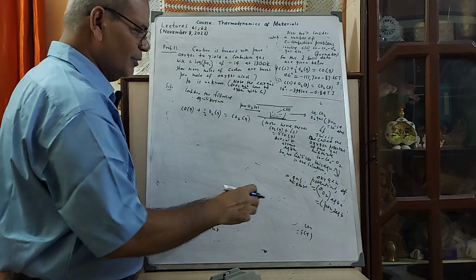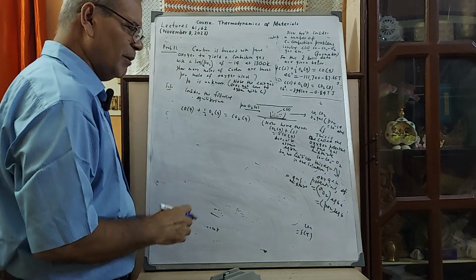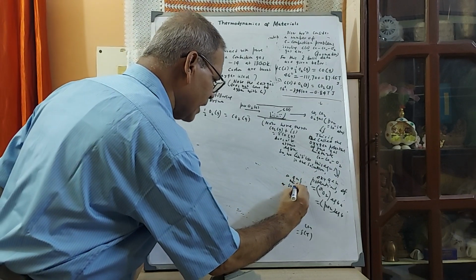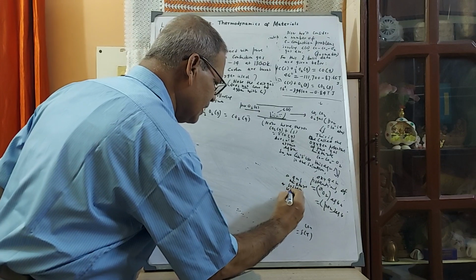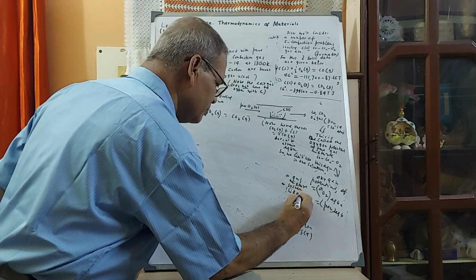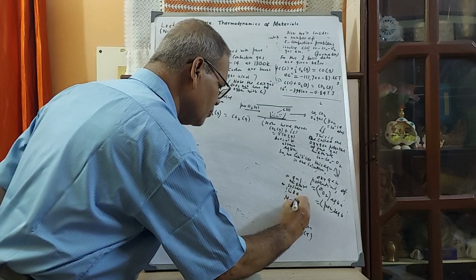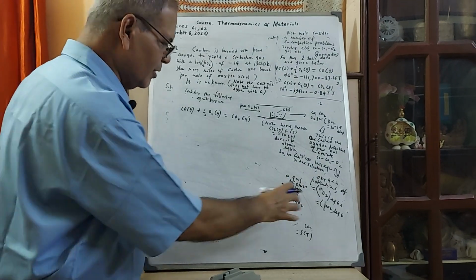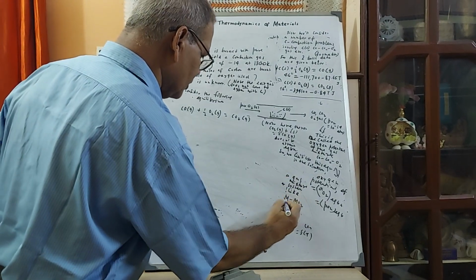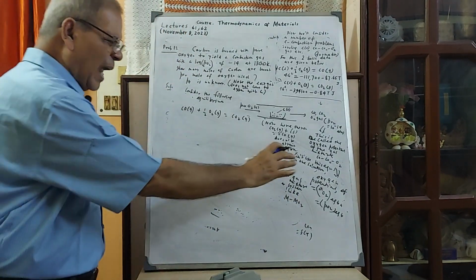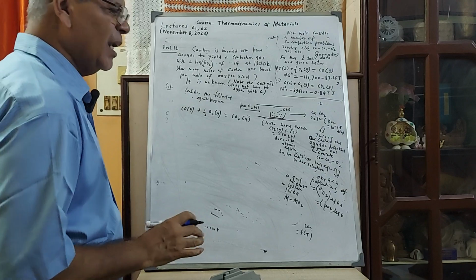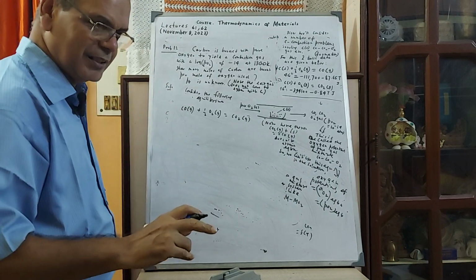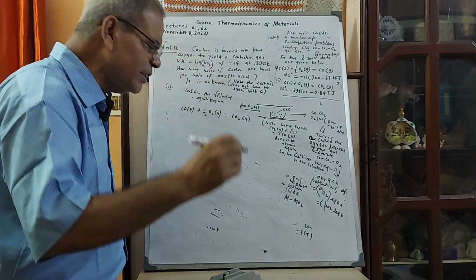So hence PO2 at equilibrium. The oxygen potential of a gas mixture or system, like a metal oxide MO2 with oxygen involved, is a very important term in blast furnace and steel making. The equilibrium value of activity, hence, is the partial pressure. If you ask me, sir, how do you relate it to the chemical potential? Chemical potential was mu, G_i bar.